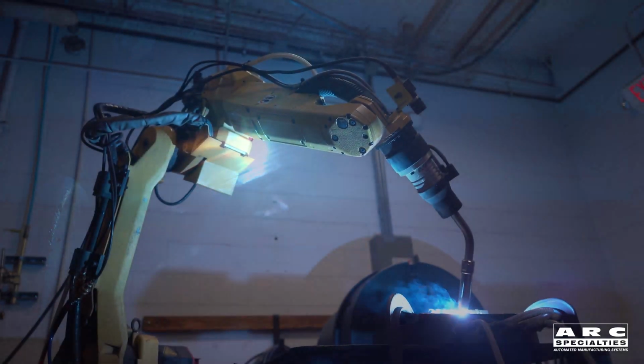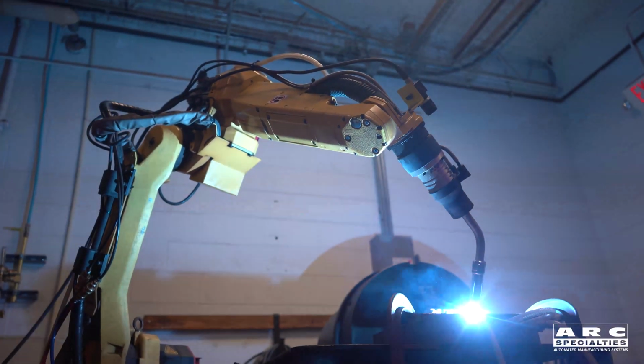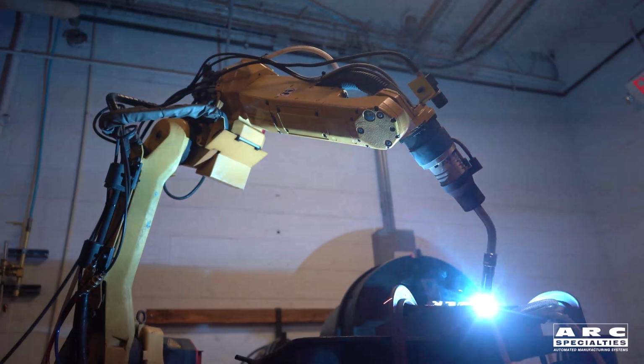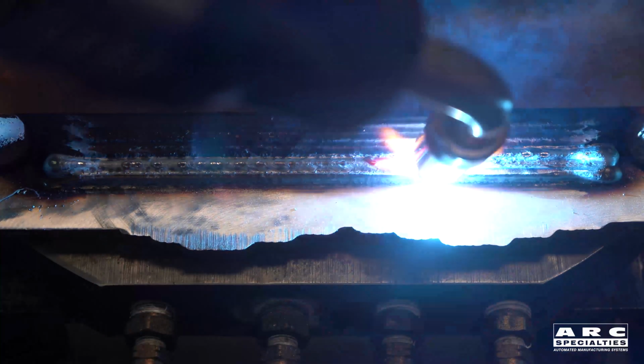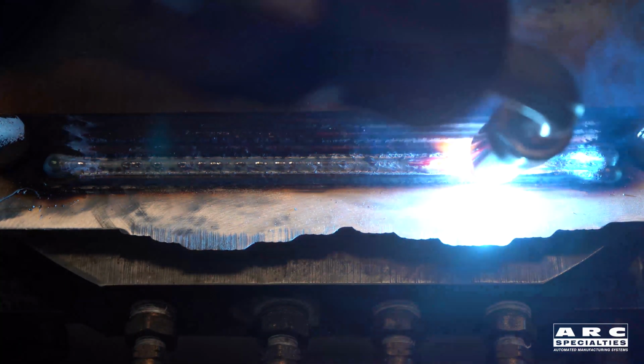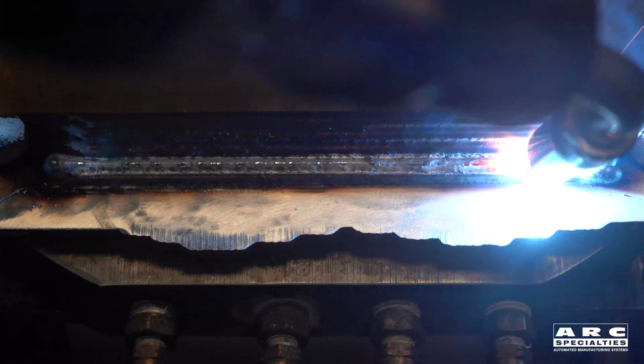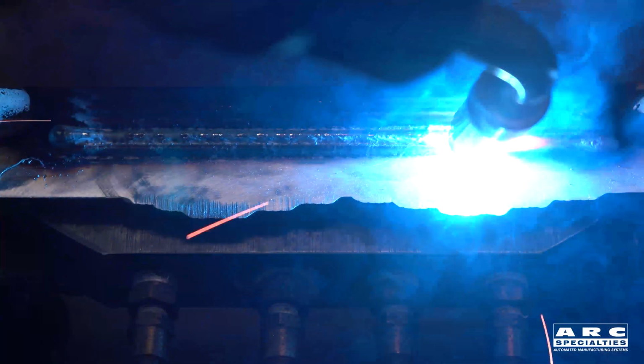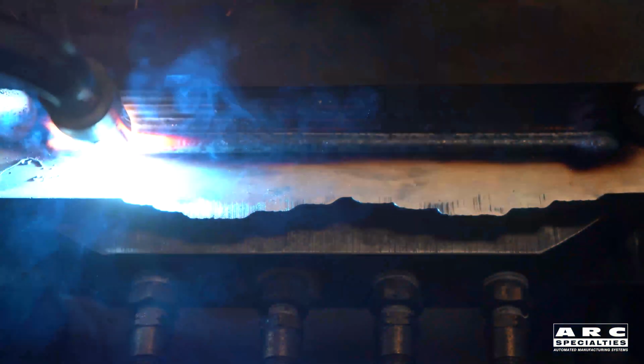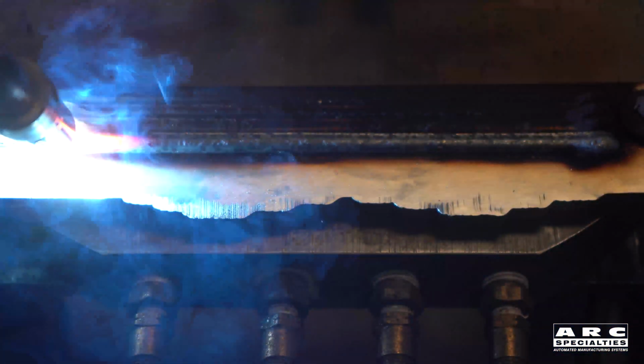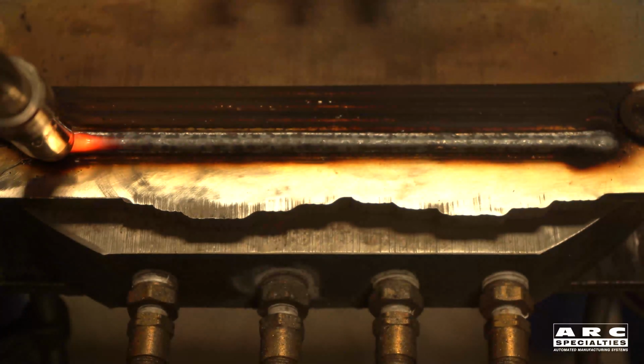We're running a water cool platen here. Minimal interpass temperature and no post weld stress relief. We want to determine just how strong a part we can make. So we're running very small beads, getting good grain refinement, getting good quenching from each pass, and getting a little bit of tempering from each pass. This is all the tricks we know to improve material properties of a weld sample.